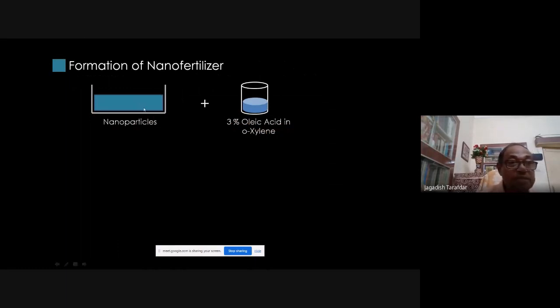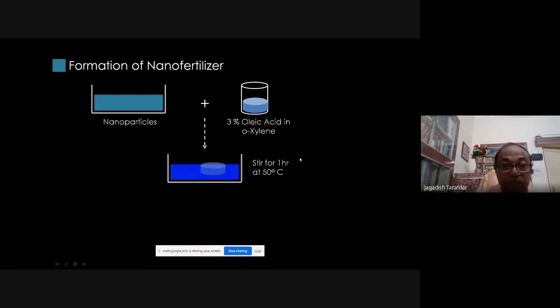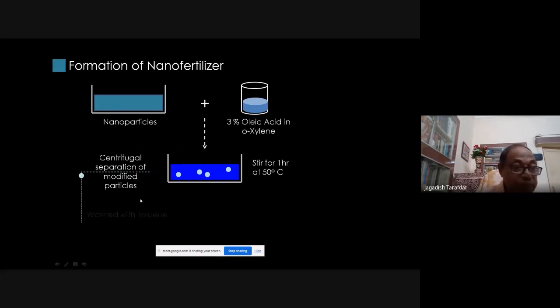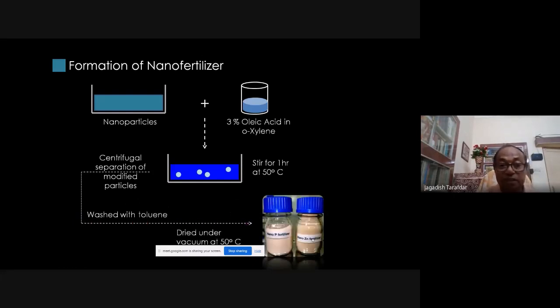Take this liquid nanoparticle, then add oleic acid with xylene and stir for 1 hour at 50 degrees centigrade. Then you do centrifugal separation of the modified particles, wash with toluene, and dry under vacuum at 50 degrees centigrade, and you will get the nanofertilizer. So you can use it as liquid fertilizer or go for solid fertilizer. But one thing I should say is that liquid fertilizer is better than solid, because during this process, due to the oleic acid coating, the size changes. Normally the nanoparticle size is 25 to 30 nanometer. After making it solid, you may get 40 to 50 nanometers. So the size increases during fertilizer formation.